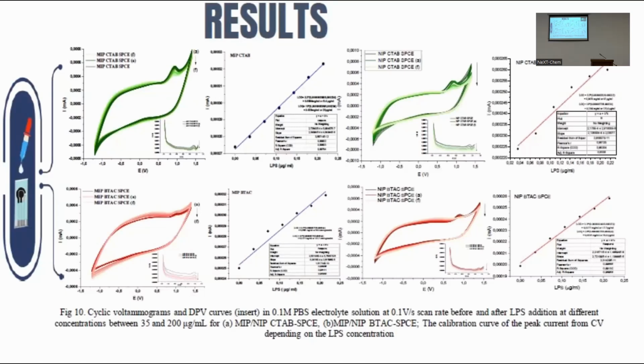For the DPV curves, it is relevant to note that the peak currents decrease with the increasing LPS concentration, a decrease that can be attributed to the insulating nature of the interface formed by the LPS molecule upon specific binding with the self-assembled polymer on the electrode surface. The proposed MIP sensors exhibit notable merits, including low limits of detection of only 8.4 micrograms per milliliter for MIP CTAB SPC and 38.1 micrograms per milliliter for MIP BTAC SPC, and limits of quantification of 25 micrograms per milliliter for MIP CTAB SPC and 150.7 micrograms per milliliter for MIP BTAC SPC.